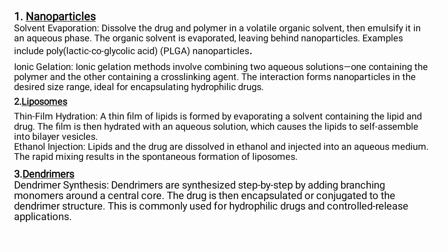Examples of nanoparticles are polylactic-co-glycolic acid, PLGA nanoparticles. Then liposomes. Liposomes are synthesized by the thin film hydration method. A thin film of lipid is formed by evaporating a solvent containing the lipid and drug. The film is then hydrated with an aqueous solution which causes the lipid to self-assemble into bilayer vesicles.